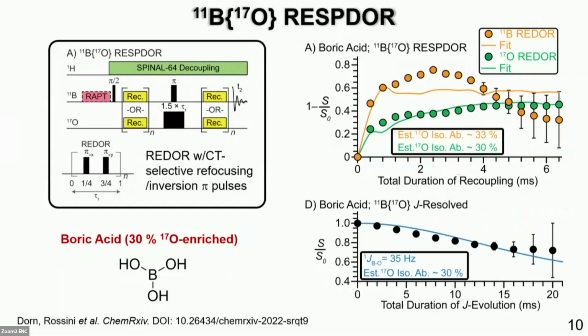Now we could also estimate the oxygen enrichment level through a boron-oxygen J-resolved experiment using central transition selective inversion pulses applied to oxygen. But this is much more time consuming because of the short boron T2 and the small J coupling of about 35 Hertz.